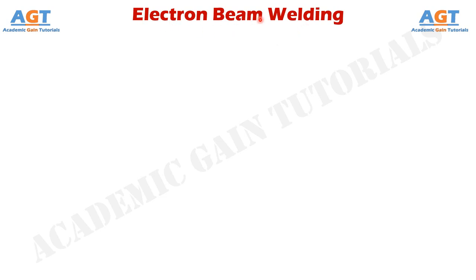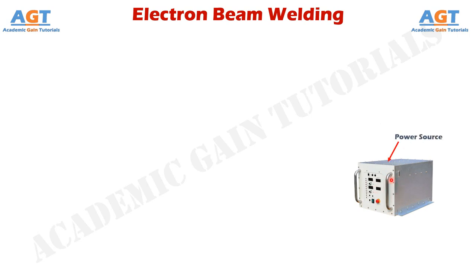So, let's look into the working process and major components used in electron beam welding. Here we have a power supply that will run the entire process. This electron beam welding process uses a continuous power source to supply power for continuously generating a beam of electrons throughout the welding process. The voltage range of welding is about 5 to 30 kilovolts for low voltage equipment or for thin welding, and 70 to 150 kilovolts for high voltage equipment or for thick welding.